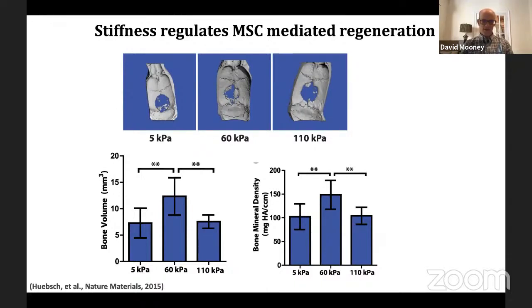In this case, in a calvarial defect model, he took a small number of cells, transplanted them in gels that were either suboptimal for osteogenesis, either too soft or too stiff, or one that was otherwise chemically identical, but had what we consider to be the optimal modulus. And what he found was the amount of bone formation was increased at that optimal modulus that we knew was optimal for osteogenesis in vitro. So the first demonstration in the body that we could regulate the ability of stem cells to mediate regeneration simply by controlling this mechanical property.